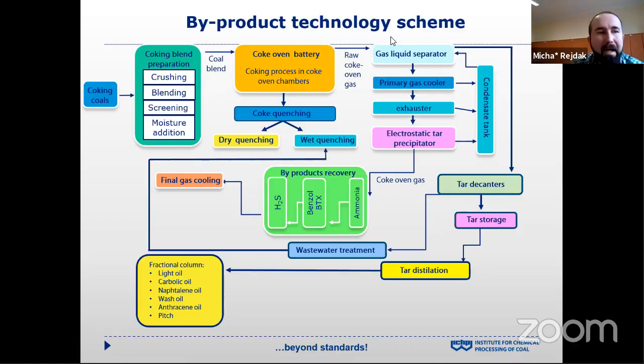The coke oven gas released during the process is sucked from the battery to the collecting main. Just before the collecting main, raw gas is cooled down from above 815 degrees to about 80 degrees by water spraying, and condensed tar is separated in a gas liquid separator. The negative pressure necessary for gas suction from the battery is generated by exhausters.